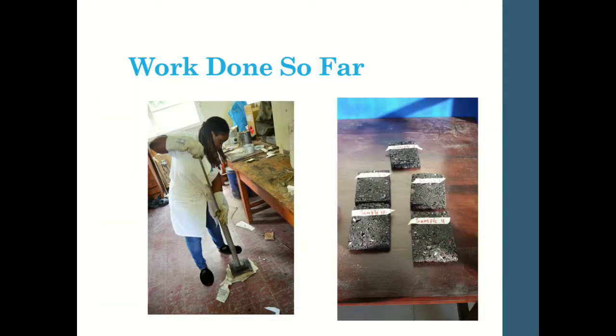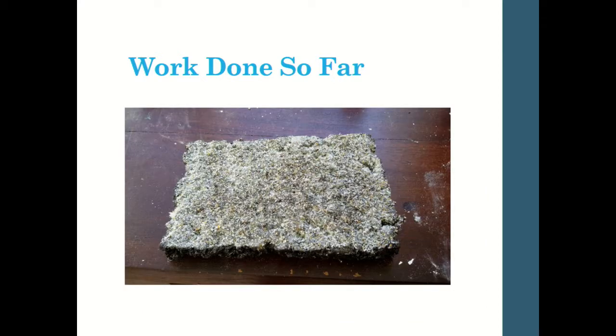Once that is done, I have to compress it using a drop hammer, which is very heavy. Built some muscles while doing this research. So I compact it, and this is the end result for my samples. Once I have that, I use epoxy and apply it to the surface to get a sample looking like this.